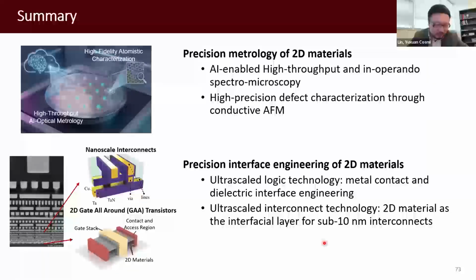Yeah. So for the reflectometry, we can focus the beam very well, so we can do a 2D mapping and give you the thickness information and K for different thickness. For the ellipsometer, I guess one beam still covers a relatively large region, so there's an averaging effect of monolayer, bilayer, etc. So what we measure is the average signal.